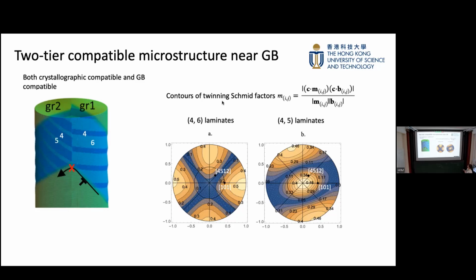What does it mean? That means if you have a 101 loading orientation here, and it formed the 6 kind of twin laminate with this kind of plane, if you have this kind of dislocation, it can drive this dislocation to move, but it cannot move further because the Schmid factor becomes smaller. And in the same way here, if you have a 4512 loading direction in this grain, and you have a Schmid factor which is 0.3 something, and if you want to move along this transition layer, it is lower on the other side. So if you want to go across this kind of interface, this just prevents the dislocation from moving across. We call it interlock or something.